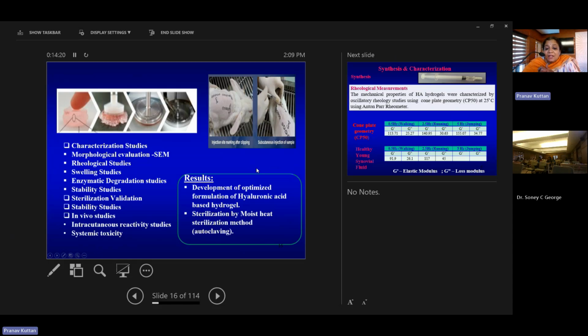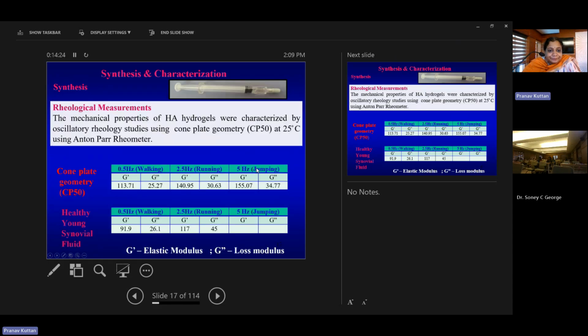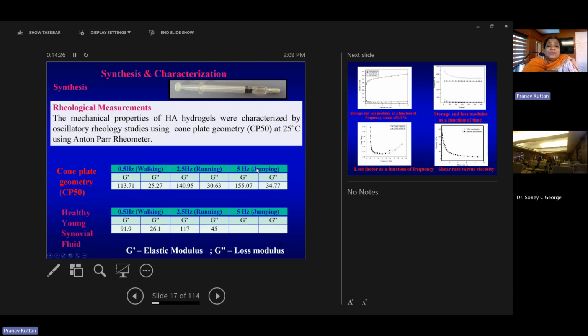That is, autoclaving was optimized for the sterilization. So I will explain it. Initially, we took this hyaluronic acid and we cross-linked it using divinyl sulfone. Divinyl sulfone is the cross-linking agent which we used for developing this hyaluronic acid hydrogel. So as you'll be knowing, divinyl sulfone is having double bonds. So that will be used for cross-linking of this hyaluronic acid.